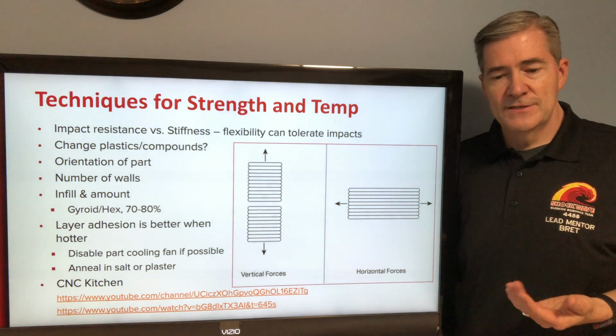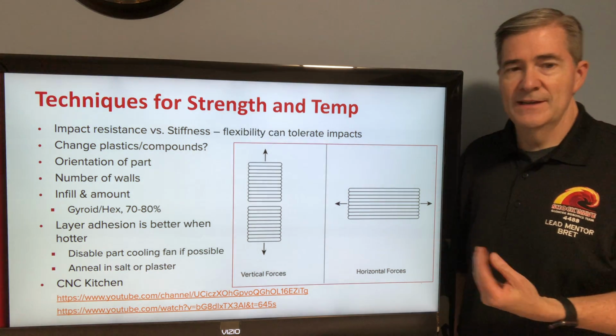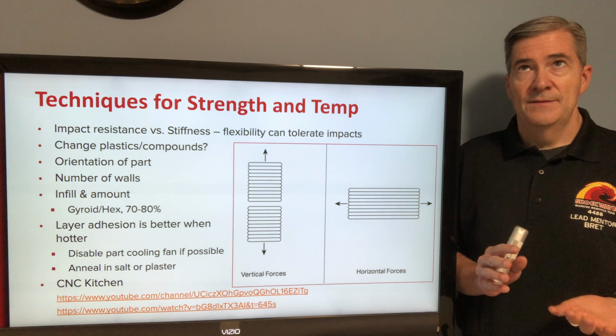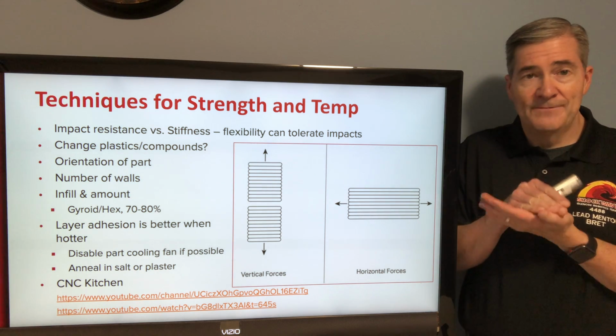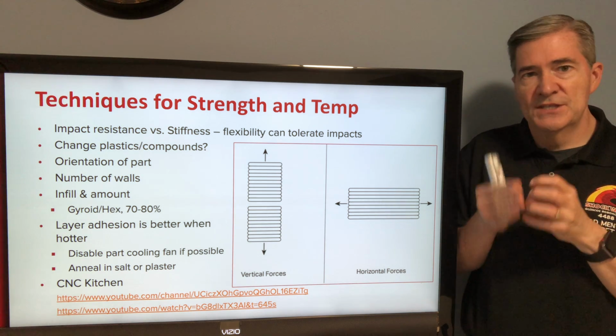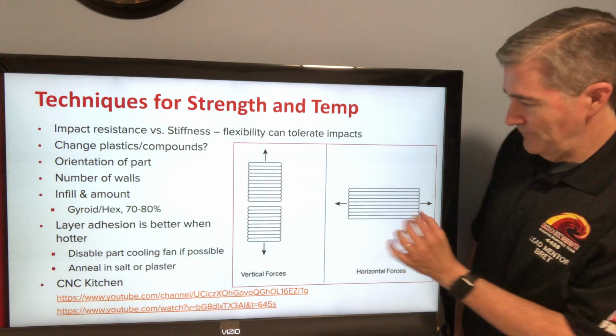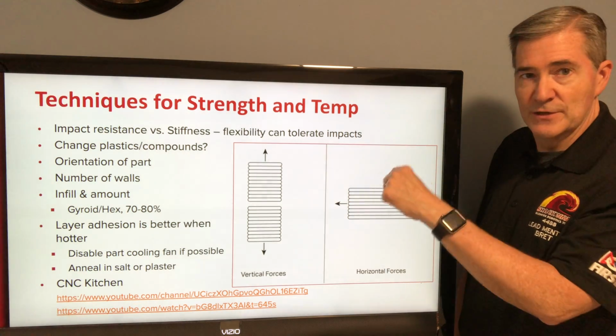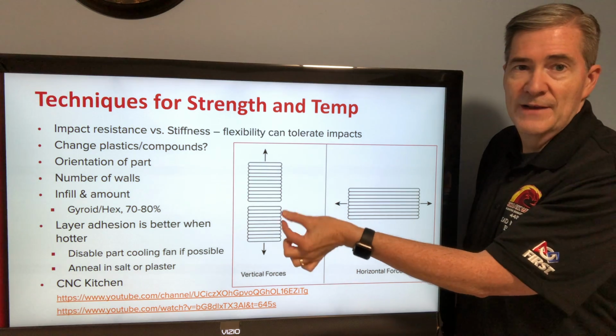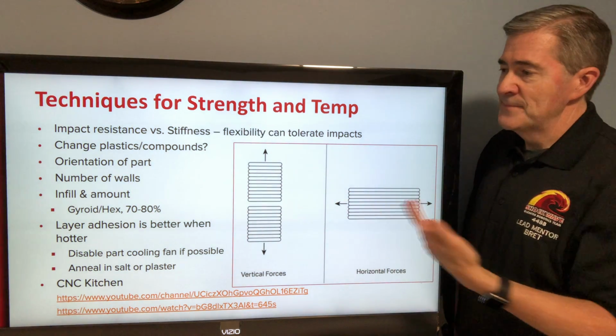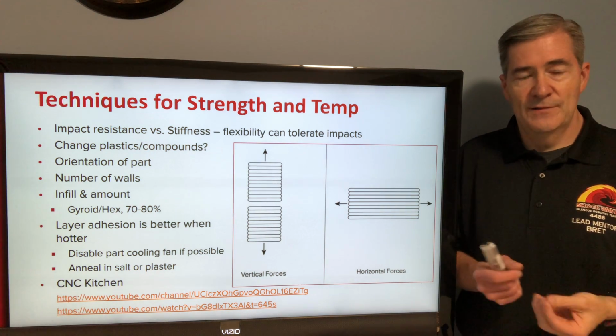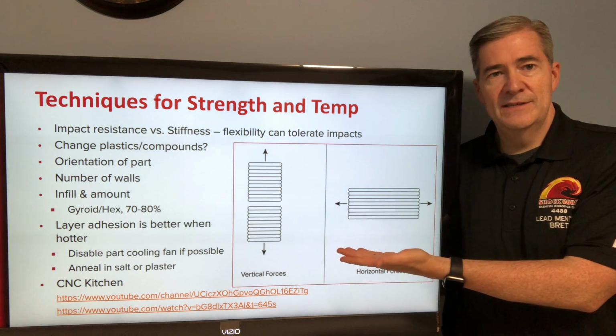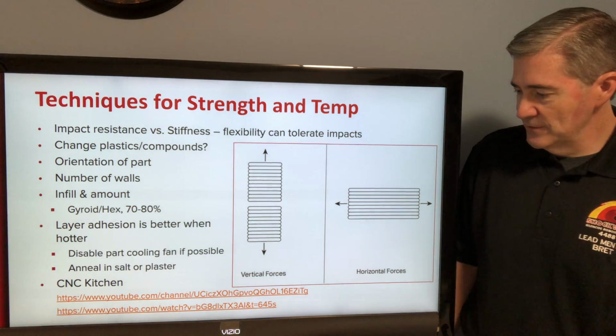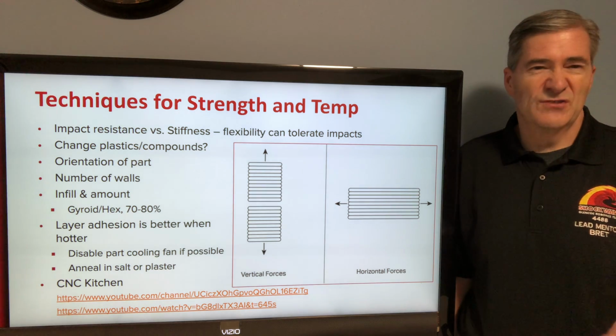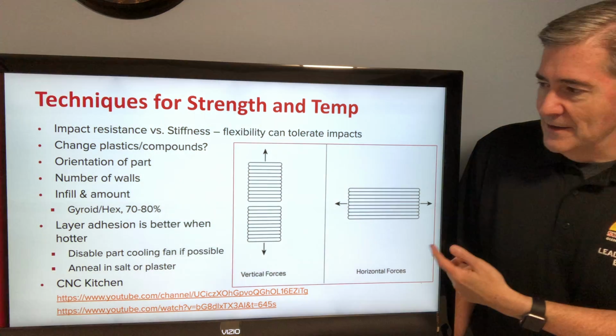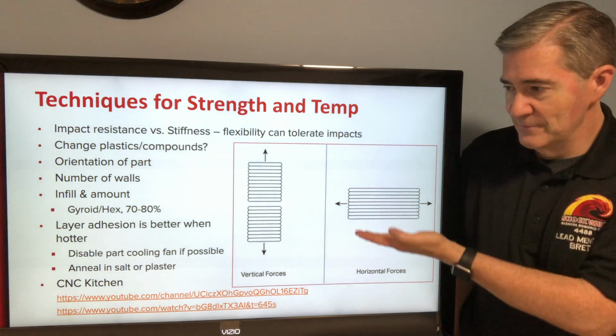But one of the other key factors in 3D printed parts and FDM specifically is the direction that the grain is going, the direction of the layers. The layer adhesion, the adhesion between the different layers, is about half as strong as the stiffness from going with the layer. So if you're pulling apart this way, or if you have a shear force that's trying to rip it down the middle, this is going to be much stronger than if you're pulling it apart where the layers can just separate, or if there are shear forces that go with the layers. So one of the really key things is, if you have directional forces on whatever your object is, pick the orientation that you print it based on what the forces are that it's going to face, so that the forces can go against the grain, because it's going to be twice as strong approximately. That's one of the big things. So think about that when you're considering the orientation of printing, because it really affects the strength.